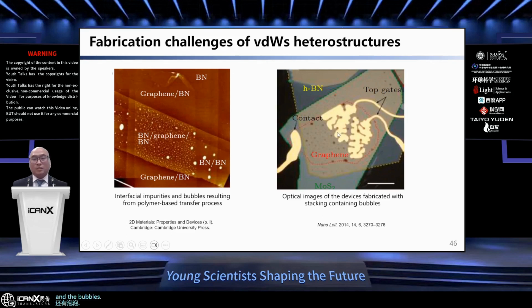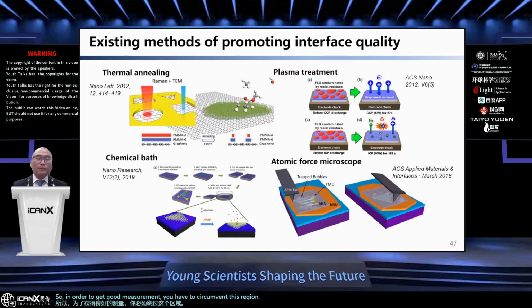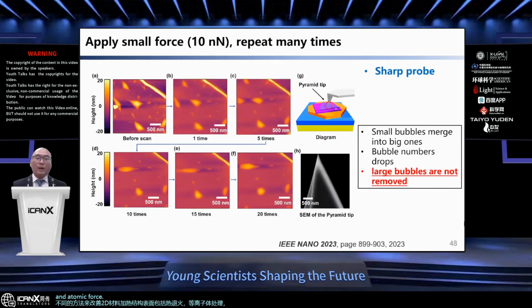So in order to get good measurement, you have to circumvent these regions using EBL. There are different methods to improve the 2D material heterostructure surface, including thermal annealing, plasma treatment, chemical baths, and atomic force microscope is one way. However, if you're using conventional sharp tips, you can only work for small bubbles. Once it becomes big, it's hard to remove.